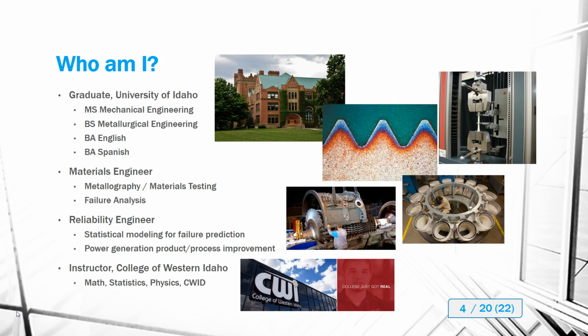An example of that you see in the photograph that I'm showing here. What you're looking at in this image is a bolt that's been cut vertically down the center. So we cut this bolt in half, and we take the half bolt and we mount it in epoxy resin, so that the cut surface is facing up out of the epoxy. And then we take that surface and we grind it, we polish it, and we get it to a mirror finish.